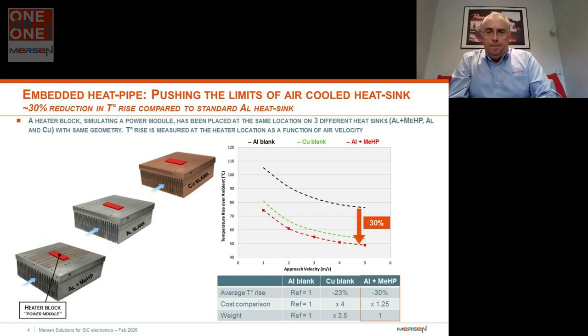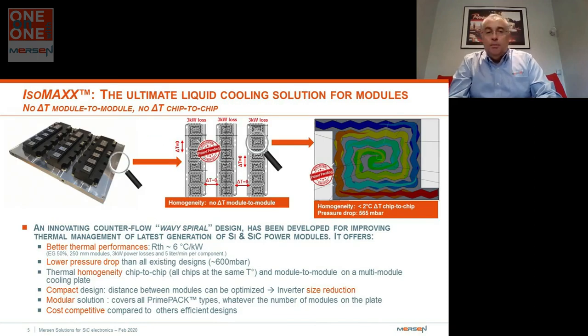For liquid cooling, Mersen has recently patented IsoMAXX. So IsoMAXX, that's really the ultimate liquid cooling solution for SiC modules. So long story short, it's a very elegant design. You see on the slide, it's a so-called wavy spiral way of transporting the liquid underneath the module, and that allows, as an added value, to have almost no temperature difference from module to module, so very nice homogeneity. And on top of that, almost no temperature difference from chip to chip inside the module.